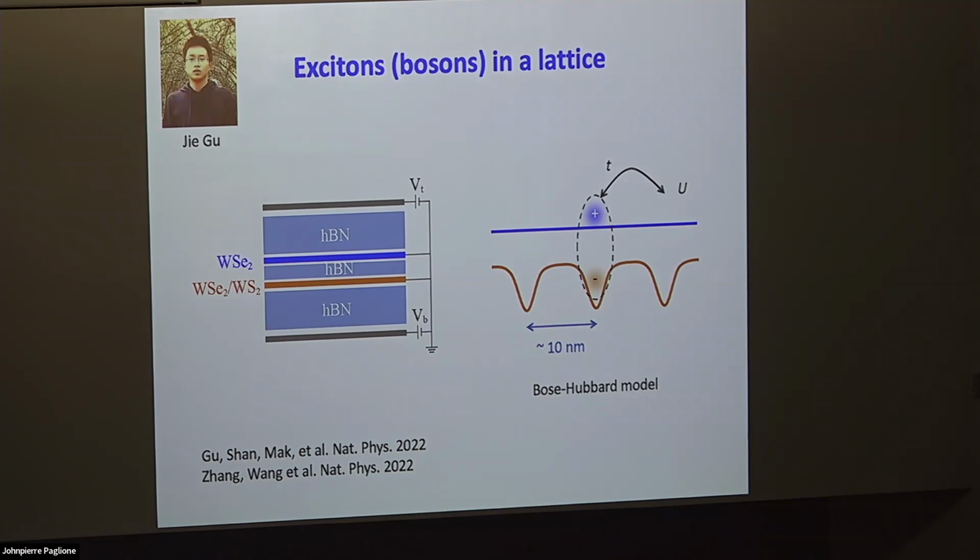Okay, it seems that there are two different questions. One is the future, one is the difference between the two. Actually, there are many technical differences. For instance, for graphene you have only one choice. There's only one graphene, right? And for TMDs you have a bunch of them, so a bunch times a bunch gives you a lot of combinations. That really allows you to play with the band alignments to begin with, which you have no degree of freedom to play with for graphene. And in graphene, the flat band actually cannot be tuned by a vertical electric field. That's another main difference in terms of tunability.